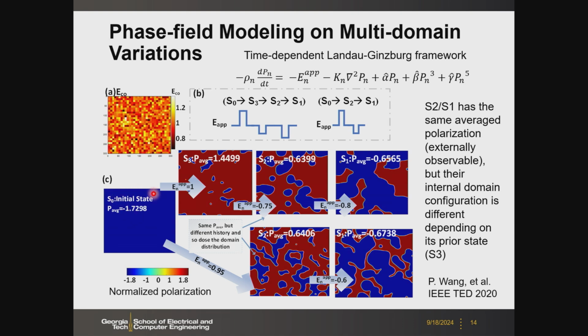Let's say we start from the ground state, where all the dipoles are up, for example, or all the dipoles are down. Then in the larger loop, we go through those steps and end up with this S1 state. And in the smaller loop, we also end up with a similar average polarization for the S1 state. But you notice that the internal configuration is different. Even though externally you observe the same polarization value, internally the configuration is different.